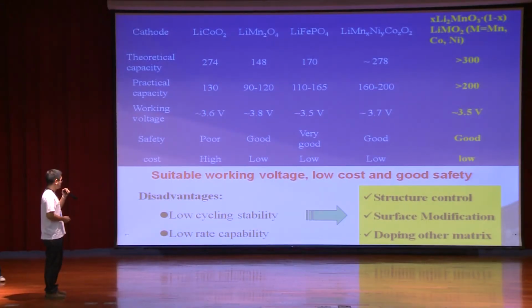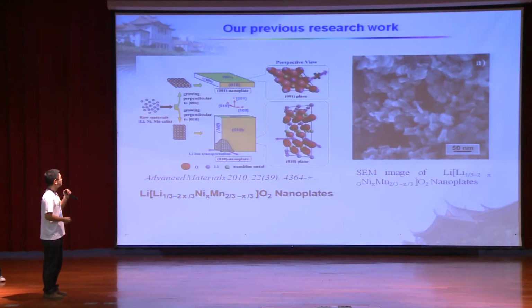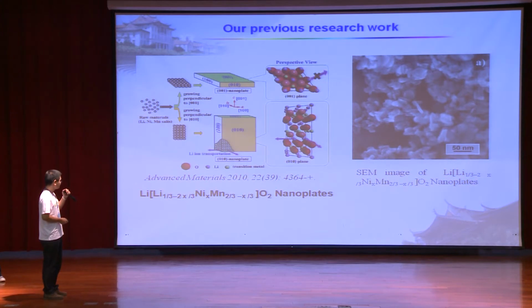But it also suffers from low cycling stability and low rate capacity. Fortunately, those drawbacks could be improved by structure control, surface modification, and doping other metals. This is our previous research work. By tuning the crystal growth habit, we could prepare lithium-rich cathode material with well-defined 010 plane nanoplates, which could greatly increase the rate capacity.